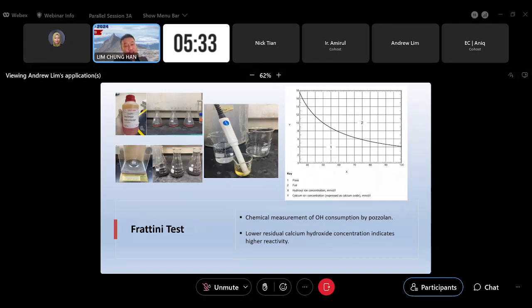If it gets consumed, that means some pozzolanic reaction is happening. So by the end of the experiment, if you end up with less calcium hydroxide, that means you end up with a lot of pozzolanic reactivity. This is what I call the artificial method, using some chemical trickery. From this test, what we're looking for is that the lower the residual calcium hydroxide that remains, you should get higher reactivity. So these are the 3 tests in theory. Now we can go to the results of all the 3 tests.